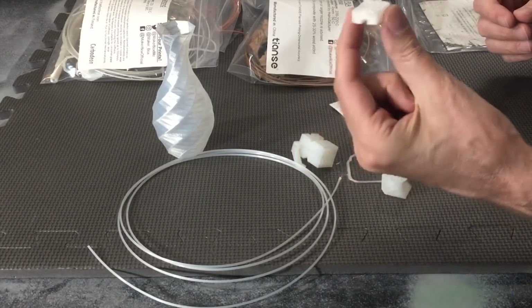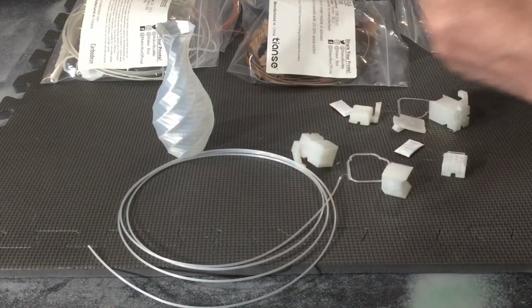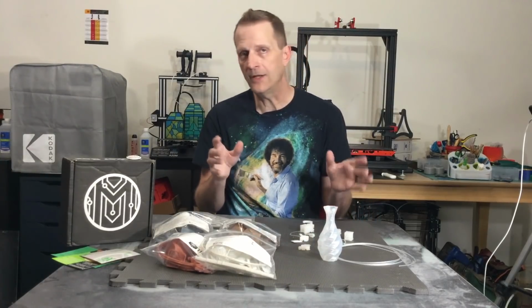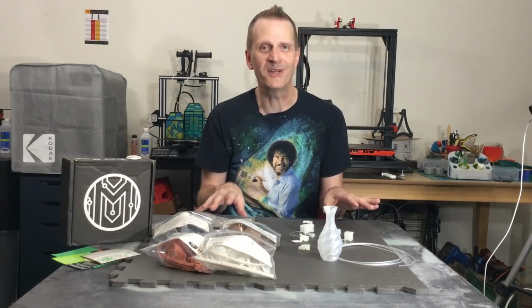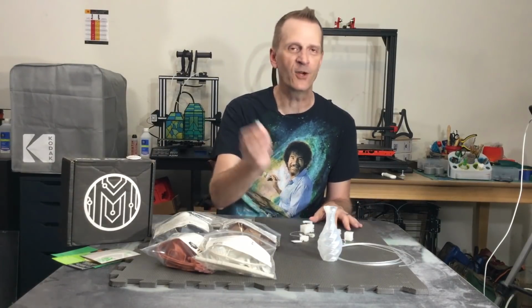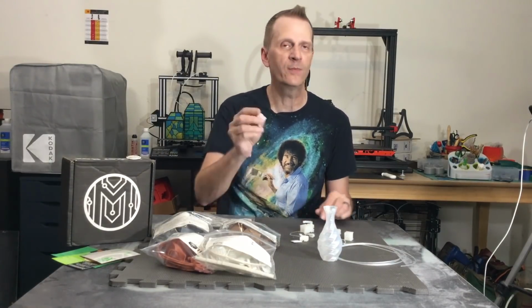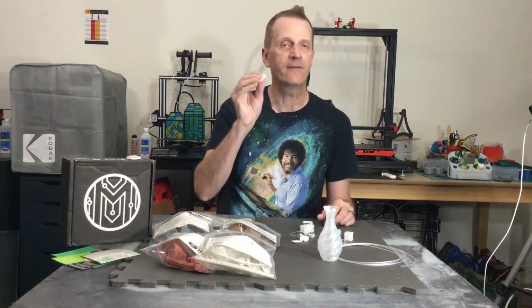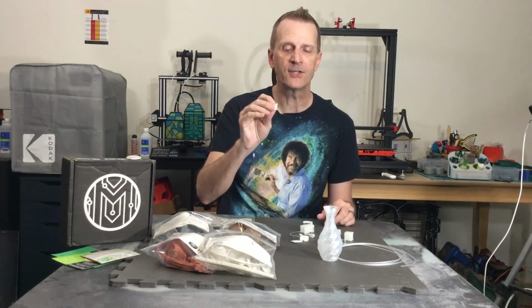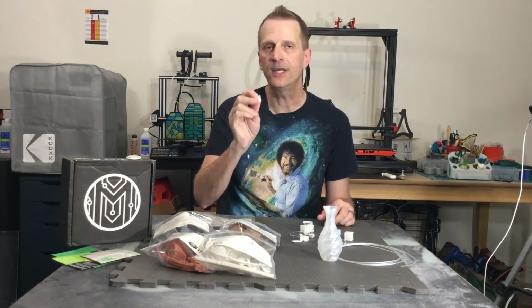It warped immediately, stuck to the hot end, and you get that kind of hot mess. So I knew right away it wasn't going to work with the sanded acrylic. There's no chance. This kind of warpage at that specific temperature meant that if I went lower, it was more likely going to stick, but I'm not going to get good layer adhesion.